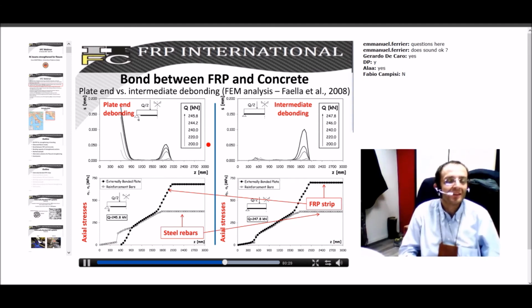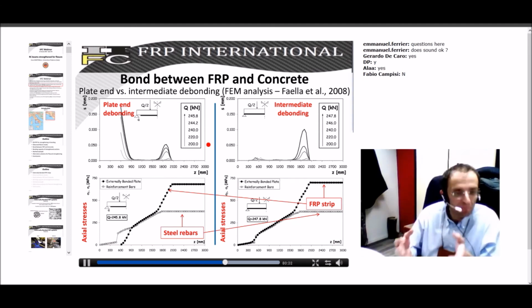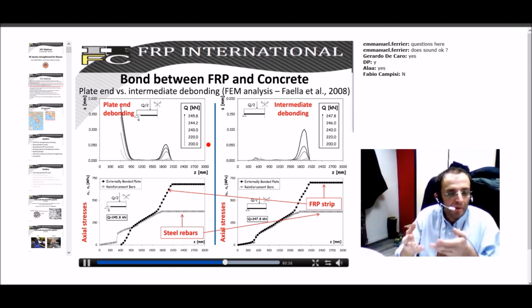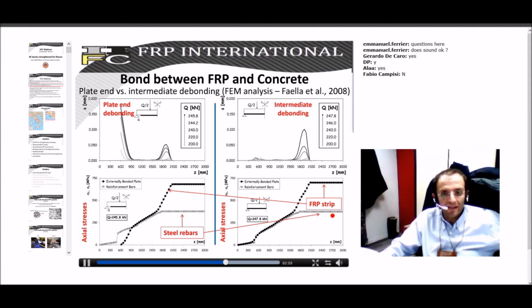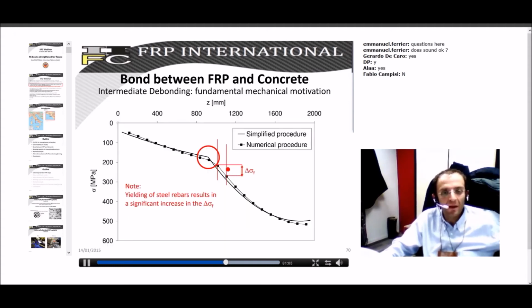So this is the key conceptual difference between the end debonding, which is basically something related to the property of the interface between FRP and concrete, and the intermediate crack-induced debonding, which results from the interaction between the actual strength of the FRP and the demanded stresses, which are strictly connected with the yielding of the internal bar. So when the internal bar is yielded, there is no further contribution from the internal bar, and all the increase in the external actions are applied to the FRP strip.